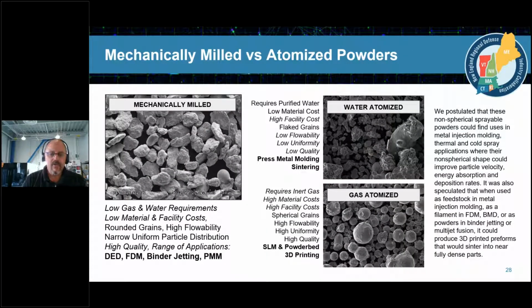And so back to those images, our material is on the left. We were able to create again a low cost, mechanically milled, rounded grain, a spheroidal material that has some qualities that make it suitable for things like directed energy deposition, potentially FDM or bound metal powder, binder jetting, and also potentially in cold spray. So we're looking at this potential value for this set of materials in cold spray. By comparison, materials that are normally produced in the metal injection molding industry, water atomized powders, or in pressed metal sintering and molding, or gas atomized powders used predominantly in 3D printing, you can see that there's quite a difference. But what we found is that the materials that we have a place in this landscape. And so again, the next step for us was, now we can make them, we can make potentially a lot of it. How does it actually fit within the manufacturing sphere?